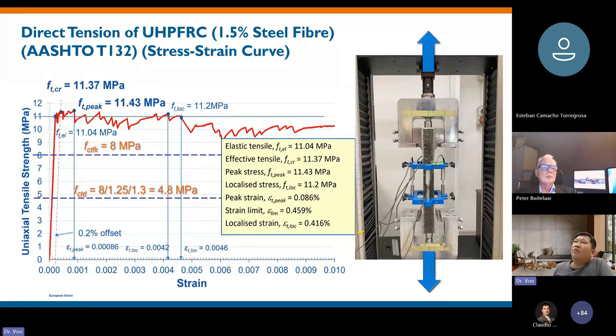So in the design of our bridges, normally we will use a post-crack characteristic tensile strength of around 8 MPa. And with the factors coming in, which are the material factor of 1.3 and the fiber global orientation factor of 1.25, basically the design tensile strength which we use is about 4.8 MPa only.